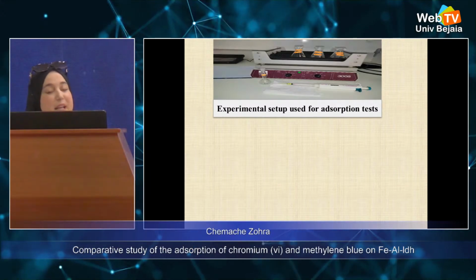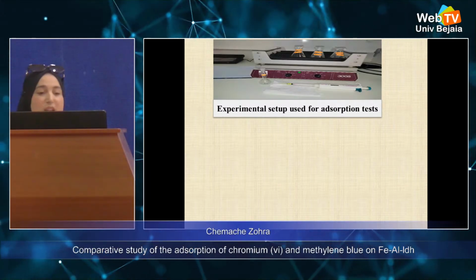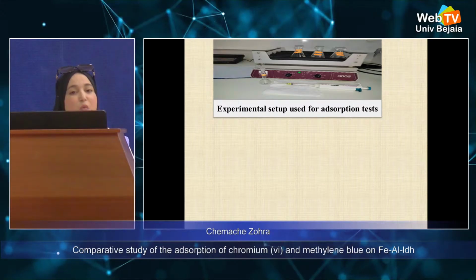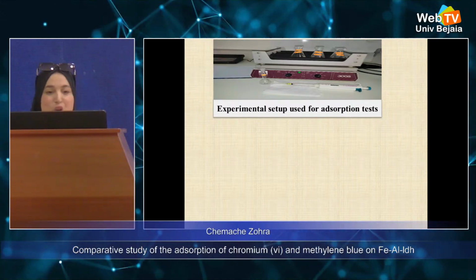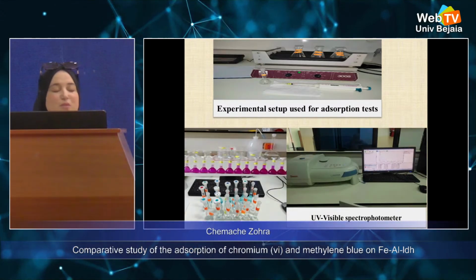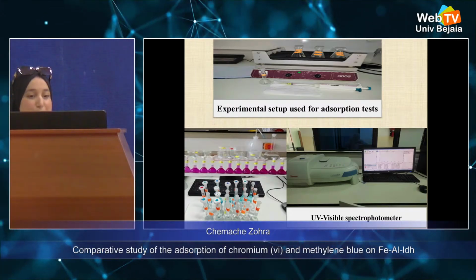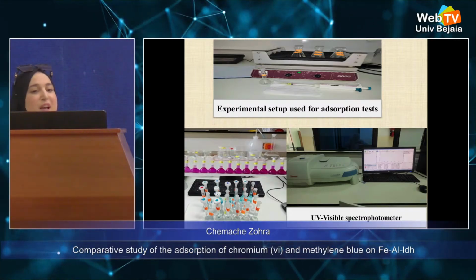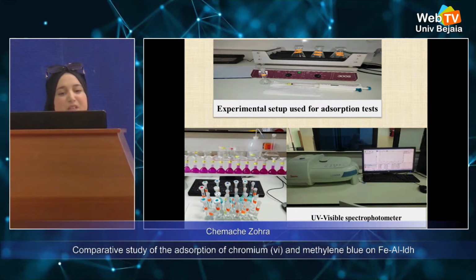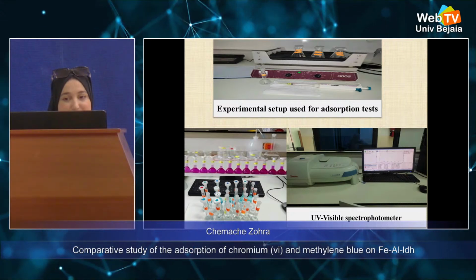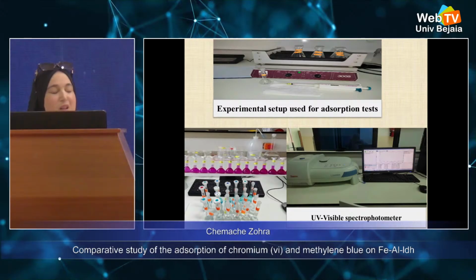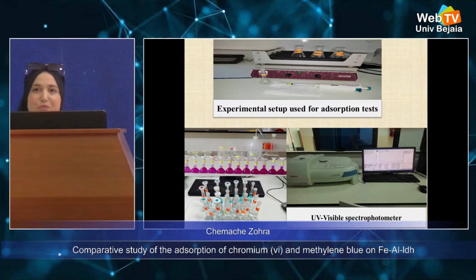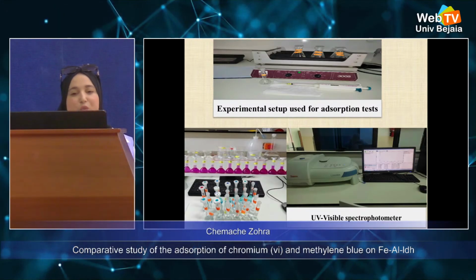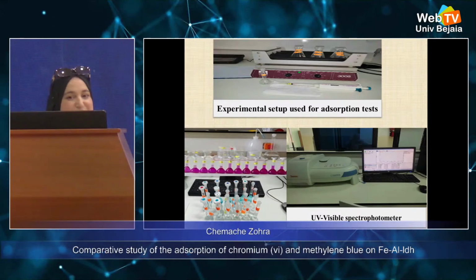Chromium hexavalent and methylene blue adsorption tests were conducted in a batch system under well-defined operating conditions. A solution at a known concentration of each pollutant is brought into contact with a fixed mass of iron aluminium lamellar double hydroxides. After adsorption, the filtrates were analyzed by UV visible spectrophotometer.